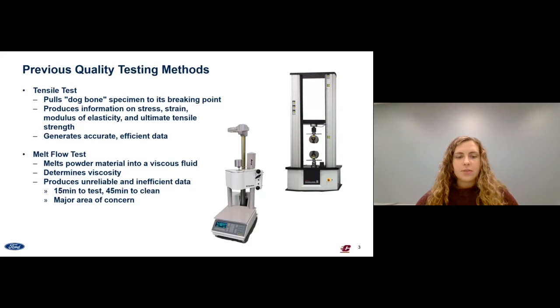Ford previously had 2 test methods that they were using to determine if their 3D printed parts were suitable for use. One of the tests was a tensile test. This machine pulls the specimen to its breaking point in order to gather information on stress, strain, modulus of elasticity, and ultimate tensile strength. This was not a main area of concern for us because a tensile test creates very accurate data that can be replicated easily. Additionally, tensile testing does not take long to complete.